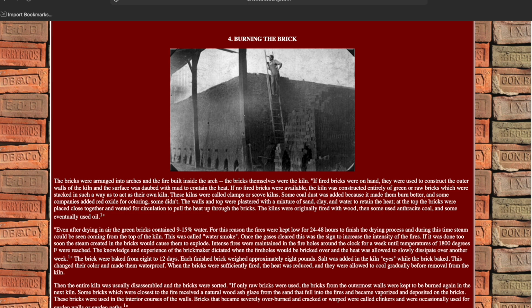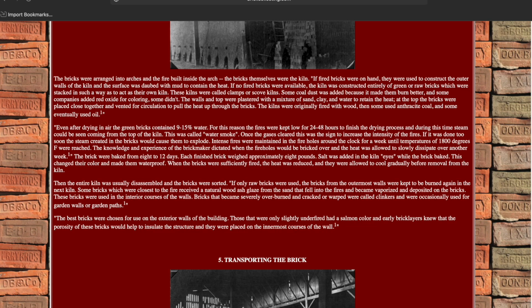The bricks were baked from 8 to 12 days. Each finished brick weighed approximately 8 pounds. Salt was added to the kiln eyes while the brick baked. This changed their color and made them waterproof. When the bricks were sufficiently fired, the heat was reduced and they were allowed to cool gradually before removal from the kiln. Then the entire kiln was usually disassembled and the bricks were sorted.